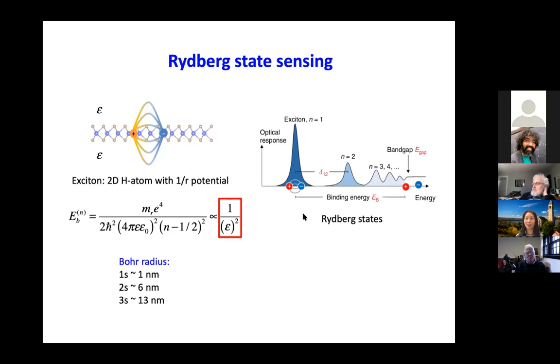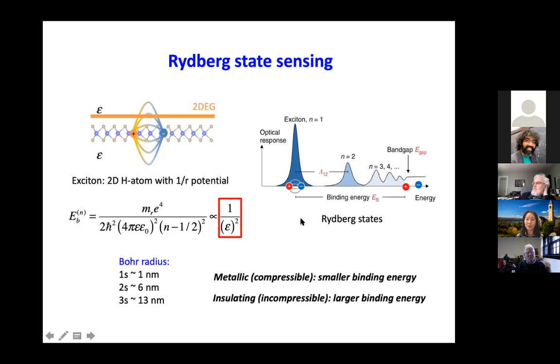So that's kind of the idea we had. So if you put some kind of a metal next to it, then you expect screening to be strong. Then the binding energy will be smaller, and also this peak will be smaller, right? And if we have a dielectric material nearby, then the screening will be less strong. So binding energy will be big, and the absorption peak will be big. So that's kind of the naive idea we had.